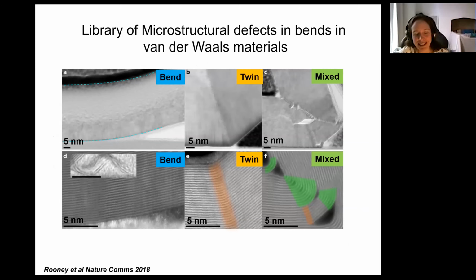Aidan looked at many, many hundreds of different bent crystals during his PhD, and he was able to produce a library of these different types of structures. And what he saw was when you bend one of these crystals to a small angle, then the crystal can accommodate this bend within its structure. So you maintain effectively perfect stacking, but just with a small amount of strain. And that's okay as long as you don't bend too far.